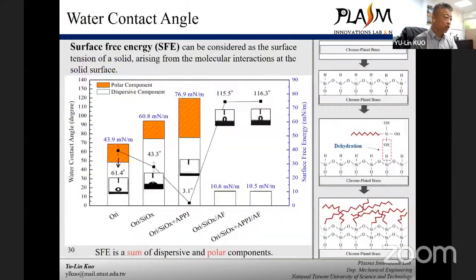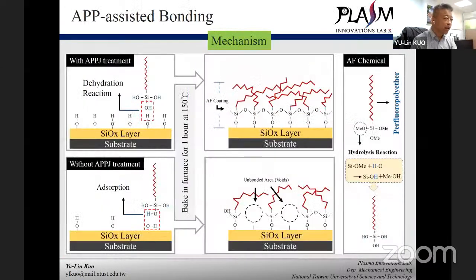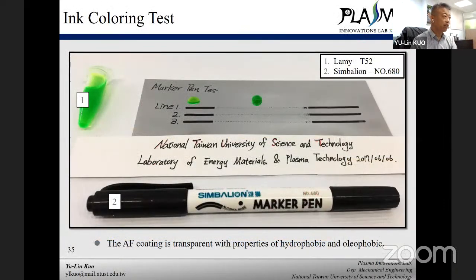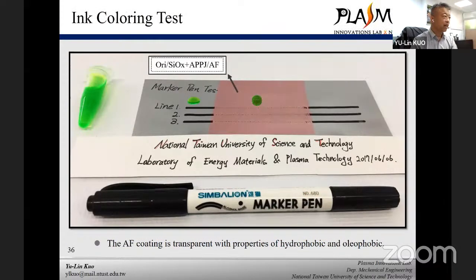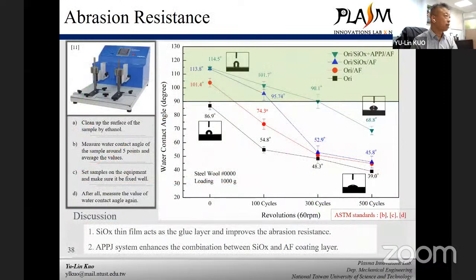So we can use the silicon oxide as the glue layer, as the adhesion layer, to adhere with the anti-fingerprint chemicals. So we can have a very good hydrophobic surface, and a very good abrasion resistance coating on the surface. So that's quite successful for the industry.